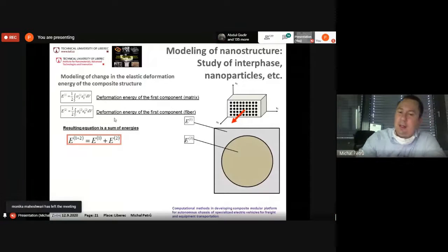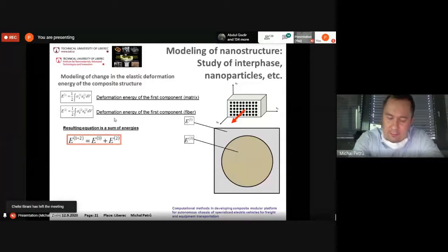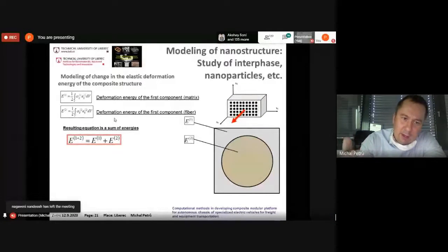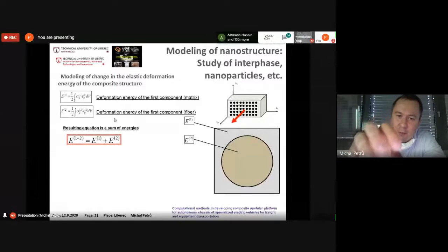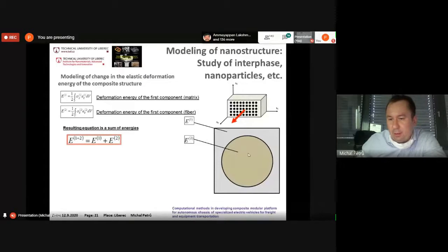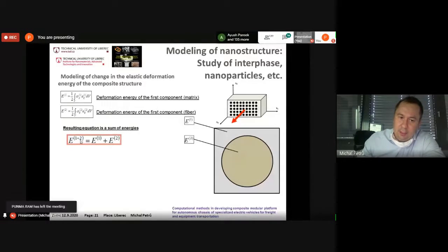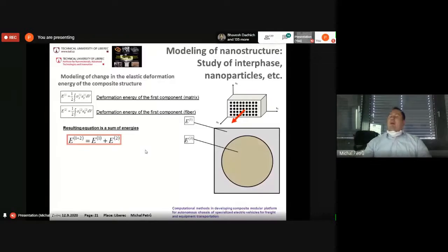Or for area. And therefore, the standard understanding will be that we calculate the deformation energy from the matrix, for example, E1, and the deformation energy from the fibers or fiber. Yeah, and therefore it's a complete sum of energies, and the resulting equation is E1 plus E2, the energy of the matrix plus the energy of the fiber.